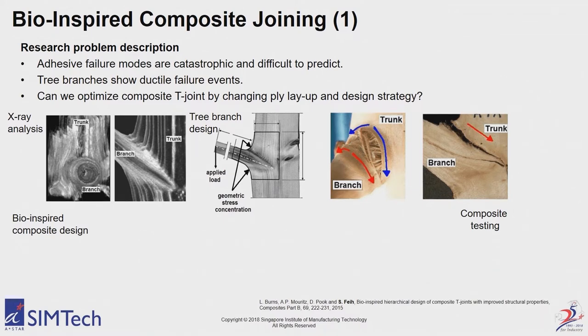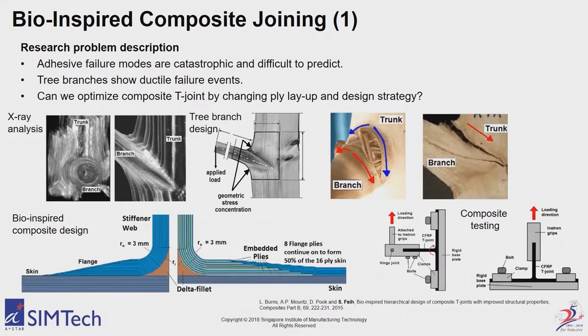And the areas in the high colors on the left pictures there, that's where the density of the fibers are actually higher. So the tree will align the fiber direction optimally. It will increase the density where needed. And we thought that is something we can mimic to a certain extent. So rather than just do a standard joint where we attach our L pieces and just connect them with adhesive, we were actually embedding them into the parent material in the trunk. And then we were testing them under bending loading and under peel loading.